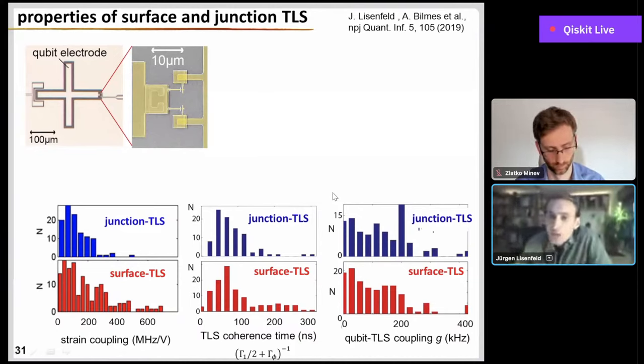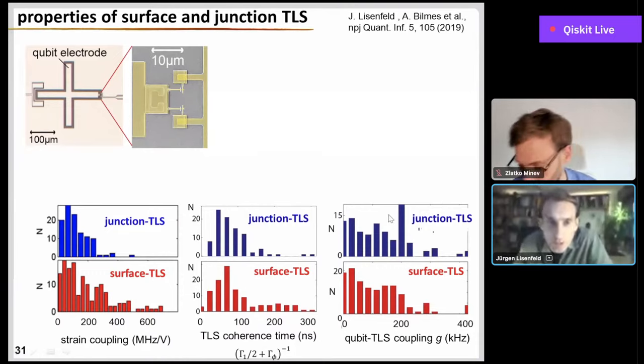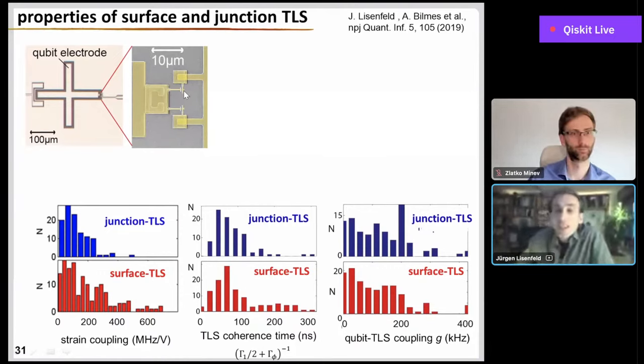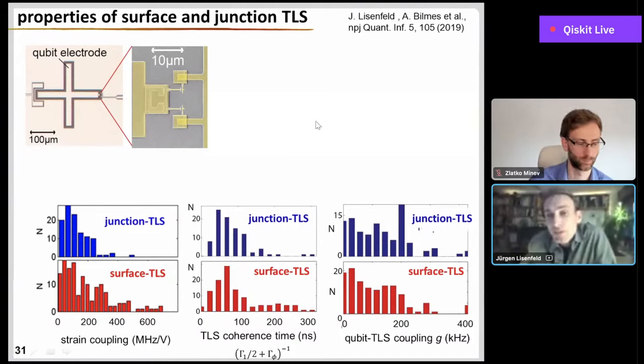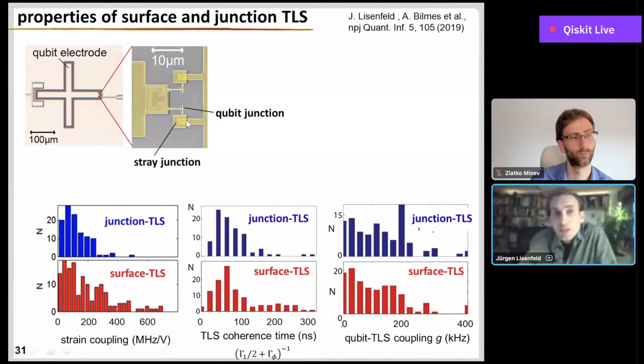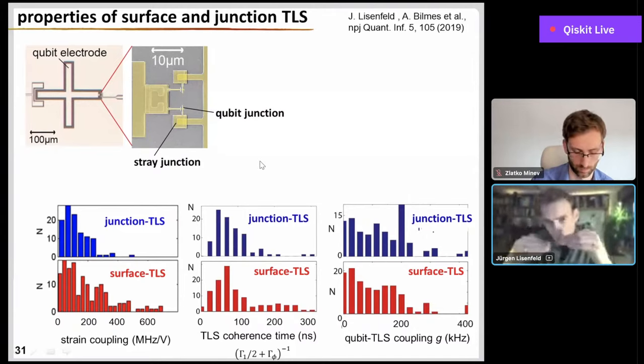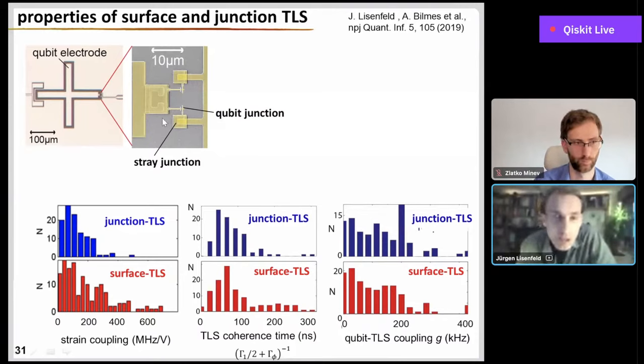Now you can actually ask, why do we have so many junction defects? I mean, we are using rather small junctions, obviously, here. And it turns out that most of these defects that we find here are living in this large stray junction. The stray junction is something that appears automatically when you do a conventional two-angle shadow evaporation. At some point, you always have to place the top electrode on the oxidized bottom electrode. And if you make the connection to the ground plane, the ground plane will also carry this oxide, of course, and that's why you make this large stray junction.